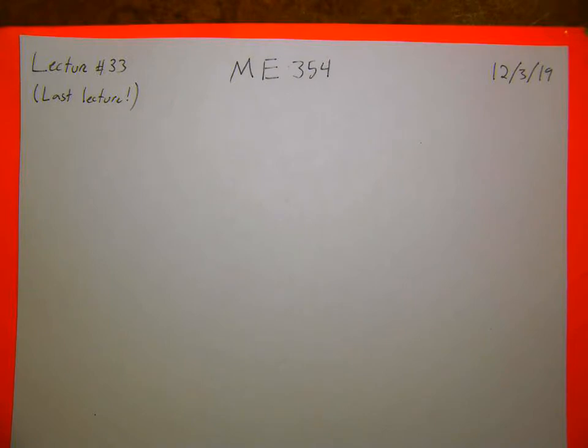If you were to have looked at the specimen afterward, these grips are little triangular pyramid things that get smashed into the sample, you would have noticed that instead of a triangular pyramid, it would have been a groove. And that groove is because that grip was slipping. All of that slipping, all of that displacement is what's giving rise to this larger strain. But what we can say is that the stress is the real stress. There's only a sample in the middle, so the stress that it is measuring is correct.